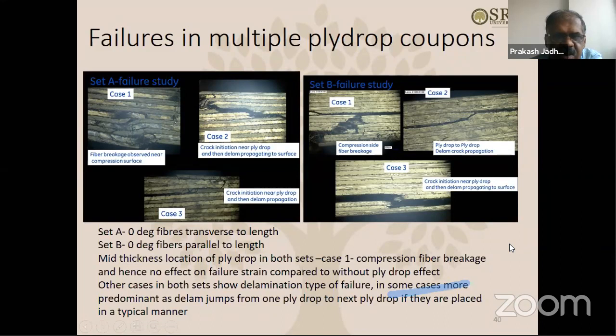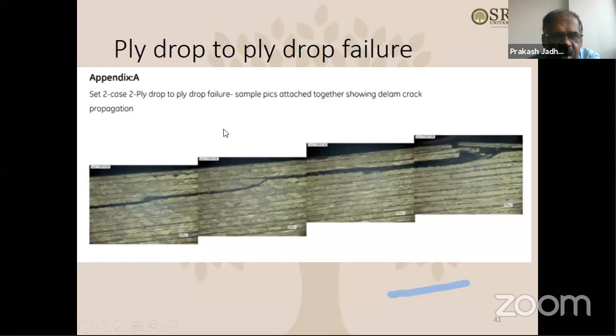I'll show you one nice picture, I think, that we got for crack jump. Yeah. So we tried to take images of this crack propagation inside the surface, and then we kind of attached them together. And then you can actually very nicely see that the crack is initiating at one ply drop, and then it is going to the other ply drop and jumping to the next ply. And then it's going to another ply drop and again jumping. Then it's going to another ply drop and jumping like this. So it's very interesting, like ply drop to ply drop, how it jumps. Why is it occurring like that?